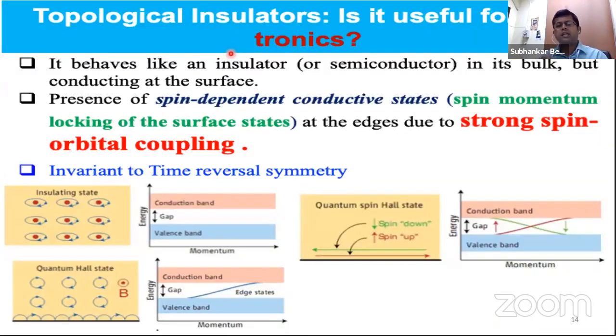Now, as I said, there are several possibilities or alternatives to the heavy metals, and one of them is topological insulators. There are plenty of talks I have seen in this conference, and everybody knows, but just in case somebody does not know, it's a special material where the bulk is insulating and the surface is metallic, because there is a strong spin momentum locking at the surface, and that exhibits a very nice metallic state on the surface, and that can exhibit a high amount of spin orbit coupling. That's actually the basic message.